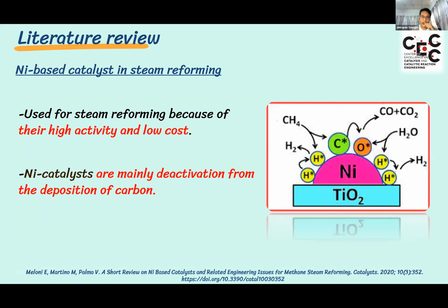Moving to the nickel-based catalyst in steam reforming, nickel-based catalysts such as nickel on silica-alumina or nickel on alumina are commonly used for steam reforming because of their high activity at low cost. Due to alumina acid sites, this catalyst tends to favor carbon deposition, so nickel catalysts are mainly deactivated by the deposition of carbon, even when operating at a steam to carbon ratio which is outside of the carbon-forming regime.